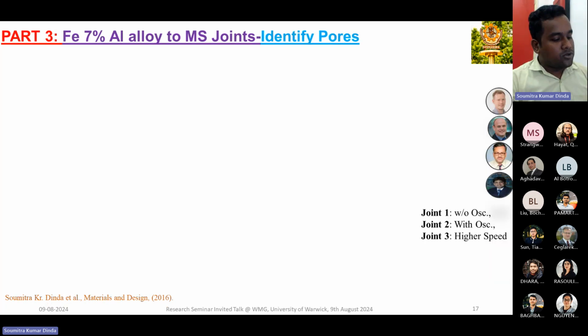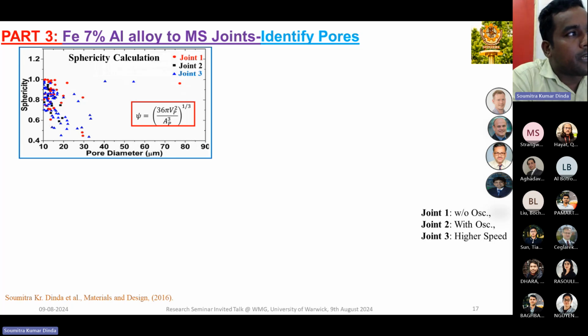We can also justify that with the help of sphericity calculation. If sphericity is close to 1, that means the pore is close to perfectly spherical. We found that in the case of joint 1, the fraction of pores with sphericity close to 1 is maximum, but in the case of joint 3, the sphericity is far away from unity. So that means the gaseous pore formation trend is stronger in joint 1.